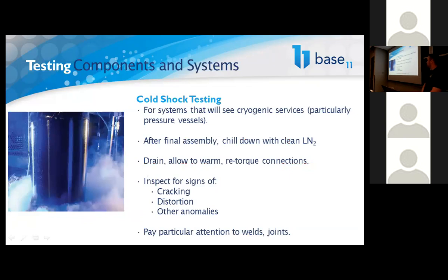So this is usually recommended for any sort of cryogenic systems. And typically your biggest candidates for failures are going to be welds or other joints. So those tend to be the areas that you want to pay attention to. And this is a good idea just to make sure, before you actually get anything to high pressures, that you're not experiencing any problems due to the thermals.